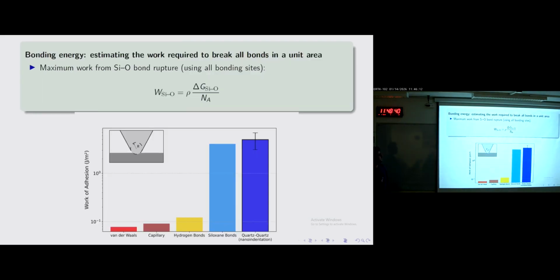Let's do another calculation and go to bond energy. So I can estimate the work necessary to break silicon-oxygen bonds if we assume that all the bonding sites on the surface are in use. What do I mean? Think of a quartz or silica surface. There are bonding sites available at the surface. If we assume that all of them are going to be used in a unit area, then I can estimate the work needed to rupture all of them. So the work necessary to break silicon-oxygen bonds is dependent on the bond density. And this comes from chemistry. It's called Zhuravlev's constant. There are about 4.9 times 10 to the 18 bonding sites per meter squared.